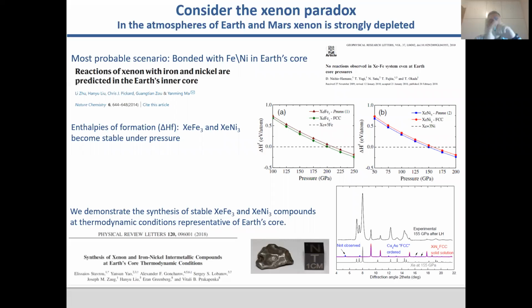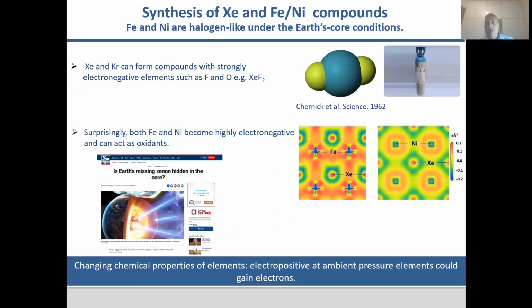So, okay, these compounds are stable, but again, let's try to understand why this is happening. Now, one may argue, okay, xenon is a noble gas, but it's not exactly a classical noble gas. Xenon, together with krypton, are large atoms with loose electrons, so it's known for more than 60 years that if there is a strong electronegative element nearby, like fluorine and oxygen, they form compounds like xenon difluoride, which is even commercially available. I think there are some practical applications like etching. So, okay, I understand xenon can find an electronegative element nearby and electrons will fly, but here we have to deal with iron and nickel.